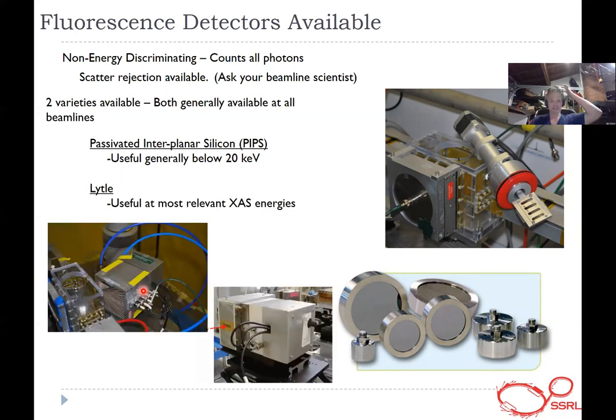A Lytle detector is also useful at most relevant XAS energies. As we go above 25, 30 keV, this is what we use. It's a stacked ion chamber of sorts. There are usually 5 sets of gold grids with argon filled around them. You ionize the argon gas and create a current, and that's how you count your signal. These are available at all beamlines. I prefer a PIPS if I can. If you can't use a PIPS, then you use a Lytle.